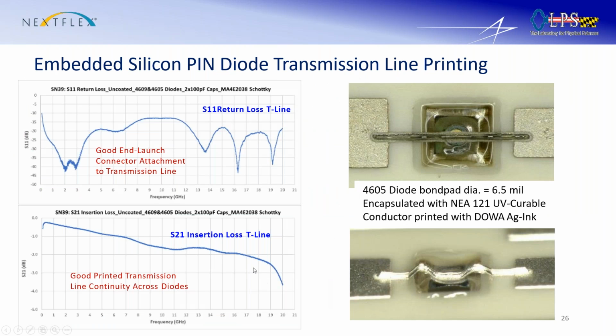This kind of shows some pictures of our first samples with it. So you can see the diode, and you can kind of see the bond pad, the encapsulation of the NEA 121, and then the printed silver right across it. The S parameters, again, we're looking at return loss and insertion loss, look very good. The return loss is below minus 10, all the way across up to 20 gigahertz. And then the insertion loss is pretty good.